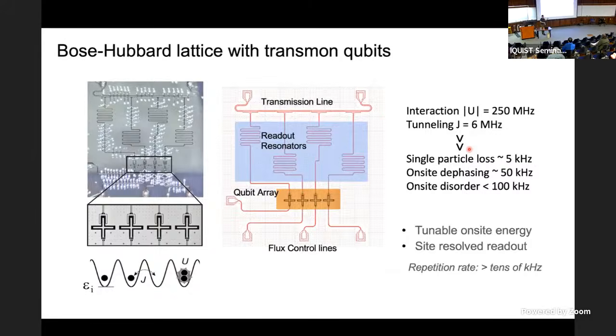I will show you in a few slides what we're accessing. So you can see in this case, we have fixed U and J. But what we can do in the end is we can vary the chemical potential or the density. So we can actually see a density-induced transition between superfluids and Mott insulators. We can have multiple Mott states with different fillings. We can have these strongly correlated superfluids.